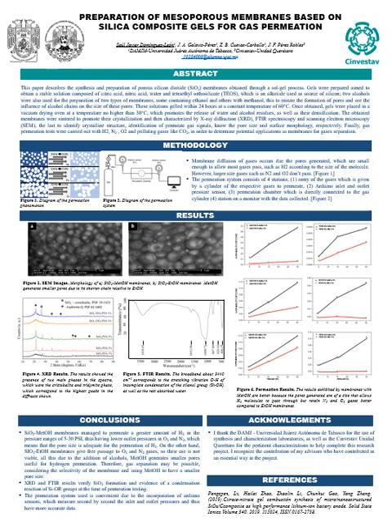The gels were formulated with the goal of producing a stable solution containing citric acid, nitric acid, water, and tetraethyl orthosilicate, an alkoxide used as the silicon source. In addition, two types of membranes were fabricated using ethanol and methanol. This dual approach aimed to ensure pore formation and investigate the influence of alcohol chains on pore size.